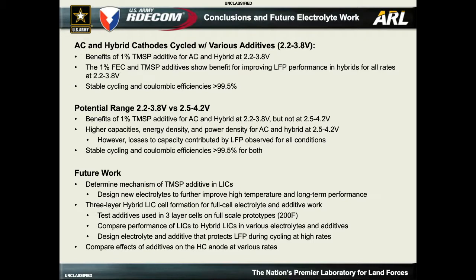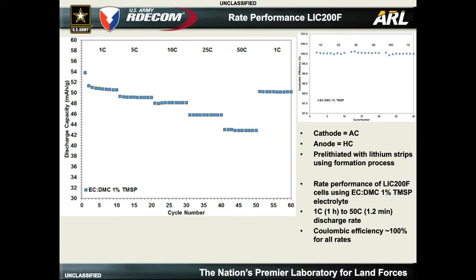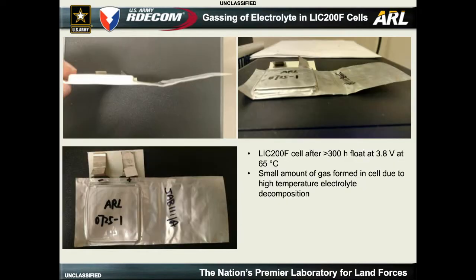And then just to conclude, the work that we're doing on lithium-ion capacitors is going to transition to fast charge batteries. With the lithium-ion capacitor work, we found that we can really charge these cells very fast. For the larger cells that we're testing, these 200 farad cells, we're charging at 50C, so that's about a minute charge. And we can do this for thousands and hundreds of thousands of cycles. So that approach of having the oversized hard carbon anode is a valid approach that we can then apply to fast charge lithium-ion batteries.